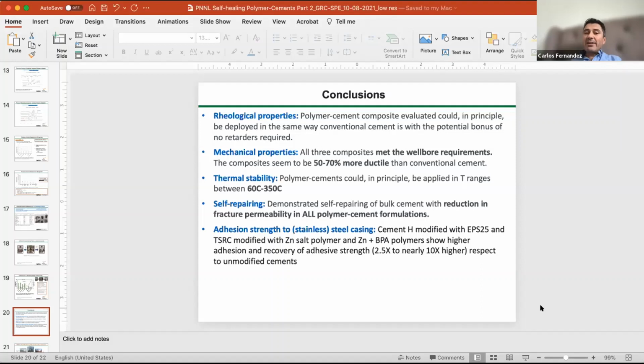Well, for the self-healing event, you have to be very careful, because if you apply the load fairly fast, and you end up generating fractures that are larger than a millimeter in size, even with the migration of the polymer to the fractures, the self-healing will occur, but it will be partial. At that point, I don't think anything will be able to heal a fracture.